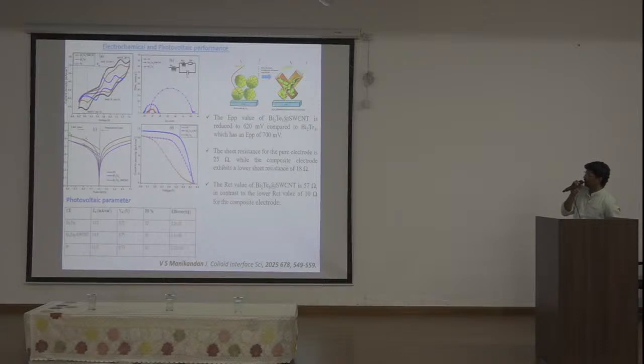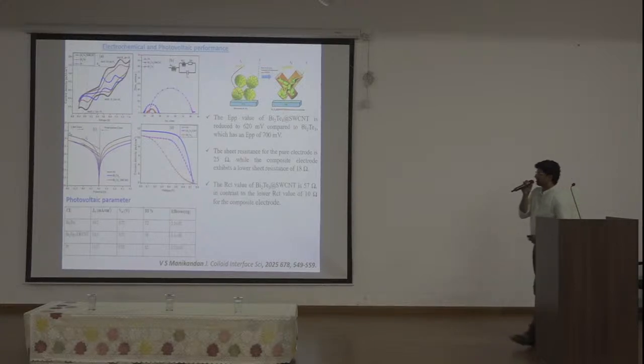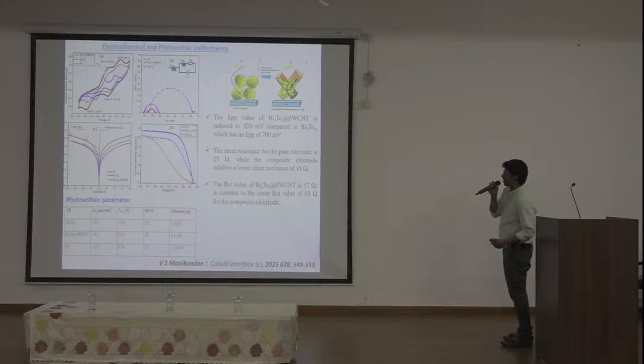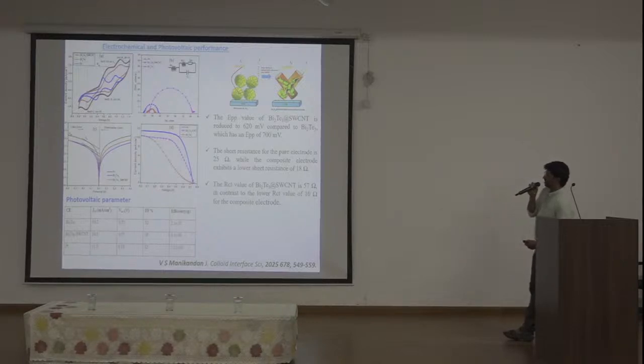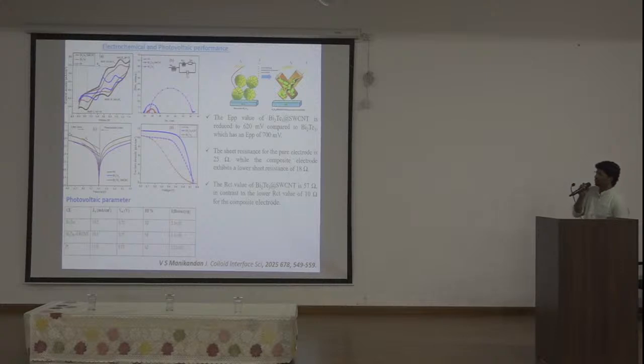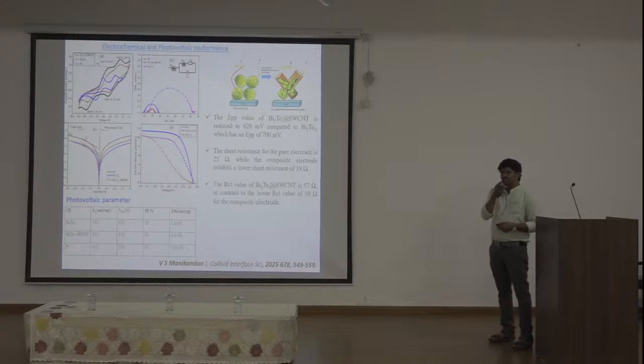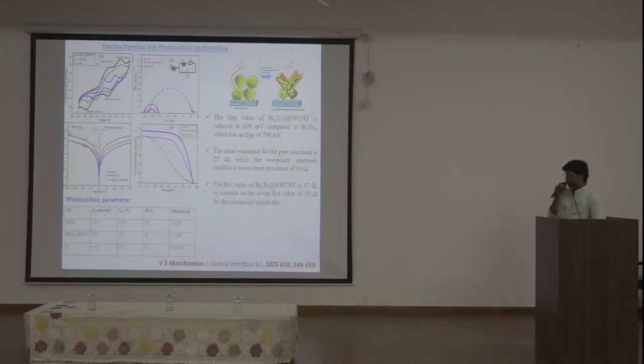We can see how the charge transfer resistance is reducing, and this is actually the blue color curve. I changed this; it was wrongly mentioned. This is the blue, the bismuth telluride CNT composition. So fill factor is one of the major things. How the electrical conductivity and the charge transport resistance behave all depends on improving the fill factor value. So only the fill factor is being tuned. I didn't show it, but I changed three compositions, with the fill factor value increasing linearly. But I have shown only one sample.